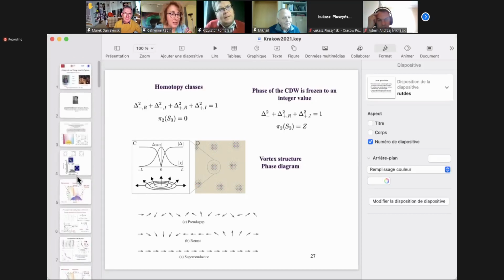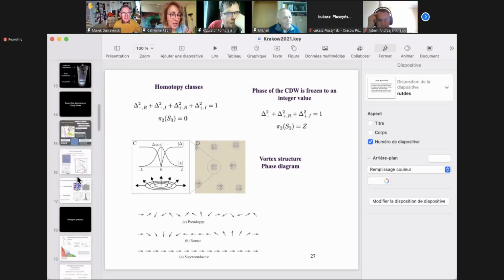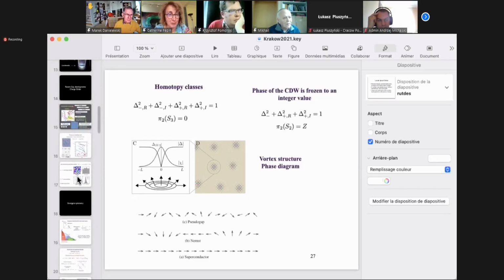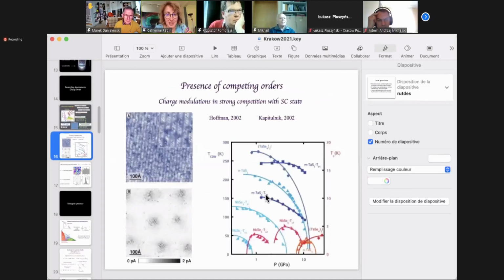Wait a second. This is a big fact for us. Take for example niobium diselenide. It has a 5 times bigger charge order than superconductivity. You sit inside the coexistence phase, you make the vortex, and you don't see anything inside the vortex. So here we see something inside the vortex.